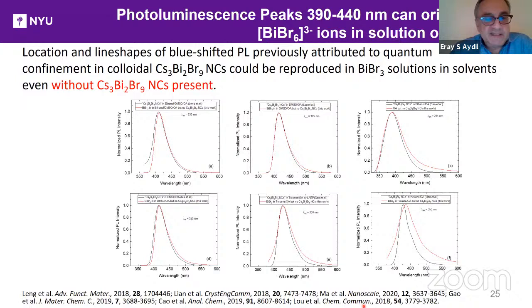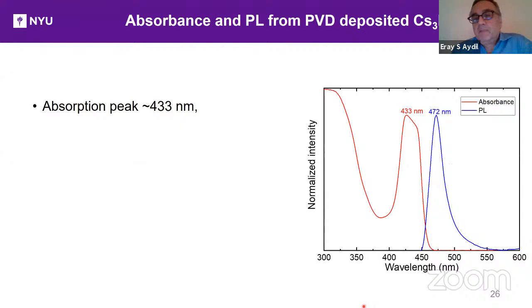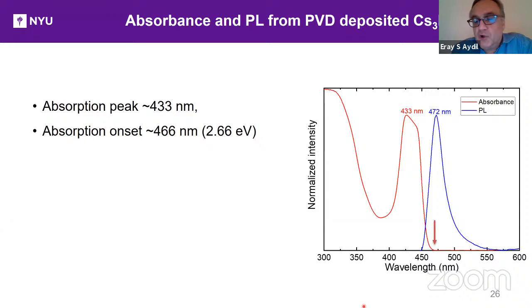So we think that there is a lot of misinterpretation of photoluminescence and absorbance data. In particular, for example, that is the 46.4% photoluminescence quantum yield from a supposed cesium-3 Bi2 Br9. Okay. So for absorbance and PL from our PVD deposited films, no matter what we do, we typically get an absorption peak at 433 nanometers. The absorption onset is at 466 nanometers. That's about 2.66 electron volts, exactly where one would like it to be for quantum cutting, twice 1.25 eV, the ytterbium transition. We observe photoluminescence at 472 nanometers, but it's weak. It's immeasurable in an integrating sphere. PL lifetime is less than one nanosecond.